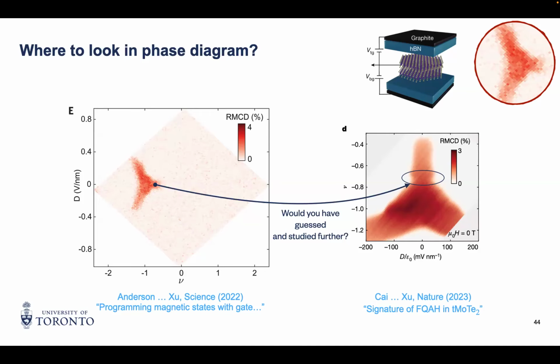So there can be a push to just get cleaner data for the sake of getting cleaner data. But what instructed you to look there, and not change material, pick a different one, and try your luck with a different system? Are we supposed to see a stepwise change? It's just a kink here. And they measured the position of that kink as a function of magnetic field. And this is what gave this Nature paper, which was the first.